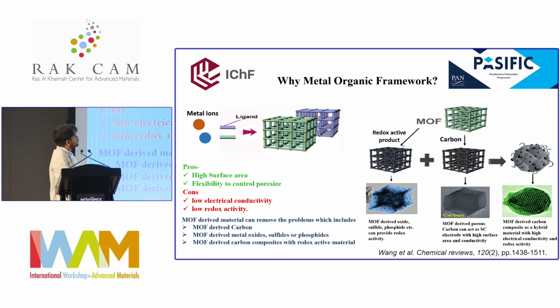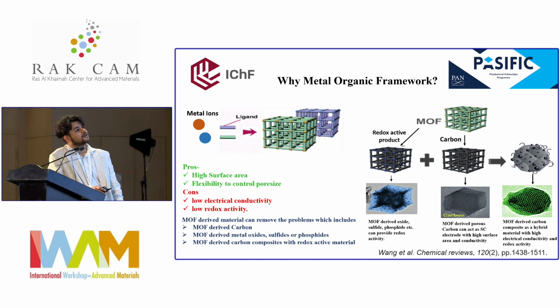We can produce different products from MOF by keeping its framework. We can produce redox active products such as oxides, sulfides, phosphides, or we can produce carbon also. We can pyrolyze the MOF to produce metal-doped carbon, and after that we can remove the metal to produce a carbon structure. Or else we can combine the redox active product and the carbon to produce a composite material, like nanosized redox active material in a carbon framework.